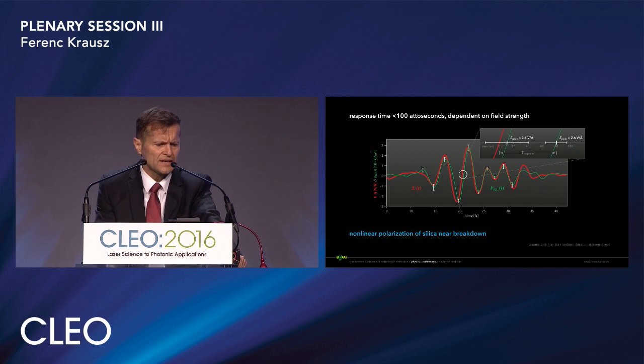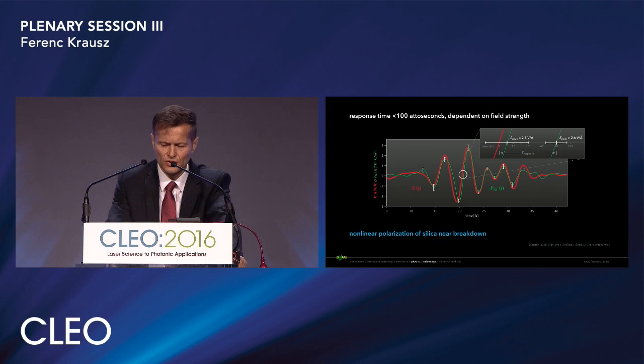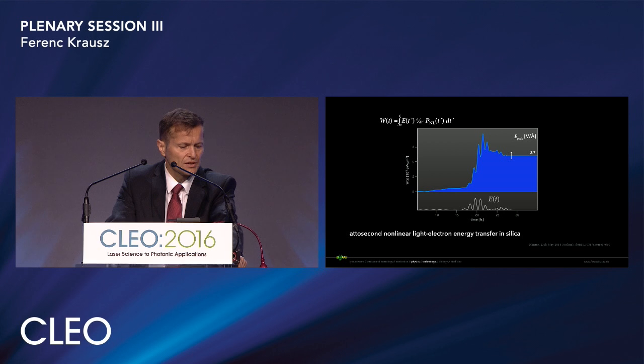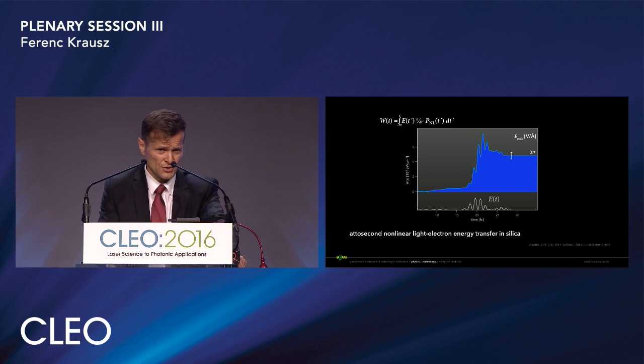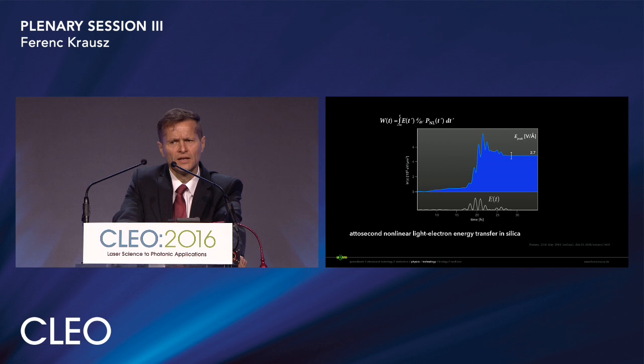The nonlinear polarization precisely known, together with the driving field precisely known, we can now calculate the attosecond nonlinear light electron energy transfer, which you see here. The initial positive delay of the nonlinear polarization with respect to the driving electric field implies a net energy flow from the field to the electronic system needed to remove the electrons ever farther away from their field-free location. Upon returning to their equilibrium position, they radiate back part of the absorbed energy into the driving field, as reflected by a negative delay of the nonlinear polarization on the trailing edge of the pulse.